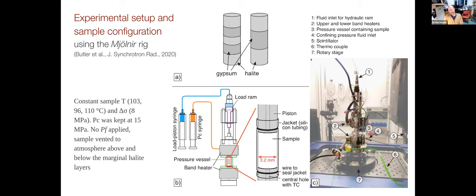Then we install this sample in our Mjolnir rig here. That sample sits in the center. This rig here sits on the CT scanner at the Swiss Light Source. This is a rotation table. So lots of connections there. We pressurize the sample here to 8 megapascal, so the confining pressure is 15 MPa here, and then we differentially loaded it. And then we did a couple of these experiments, of course, at different temperatures.